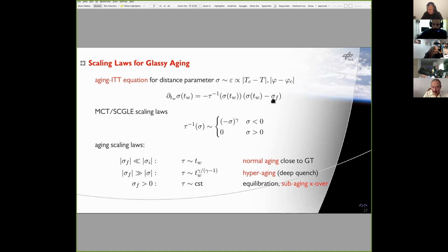If you quench exactly to the glass transition, you can set this final term to 0, and then it's even easier to solve the equation. And you see that finally the relaxation time is predicted to grow just linearly with the waiting time. So you can call this normal aging, as it has variously been done in the literature.